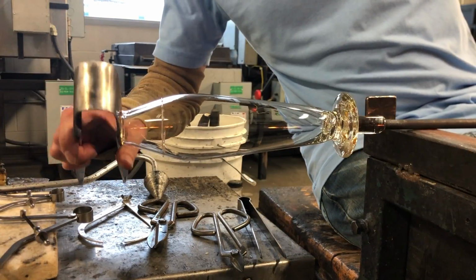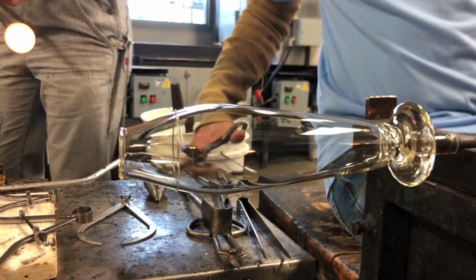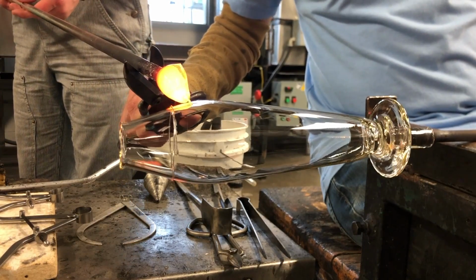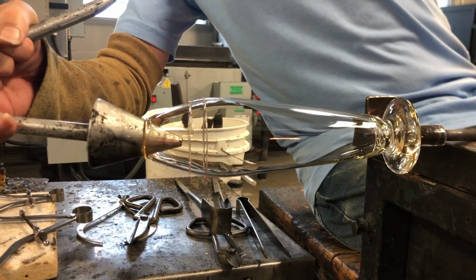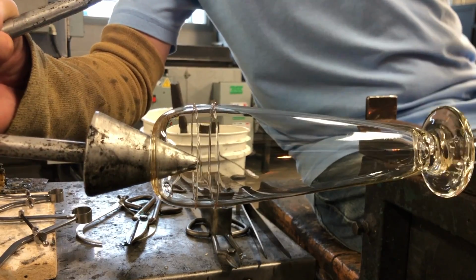Partner's gonna bring it. My object is sort of warm, otherwise that thin thread wrap won't stick. They're gonna cut and then they flip it so the hot side is down. I have to be turning before I touch, otherwise you put a big blob. And if you do it fast enough, I'm casting it off is what's happening there. By pulling really fast, that glass pulls back to a thin thread and then melts off.